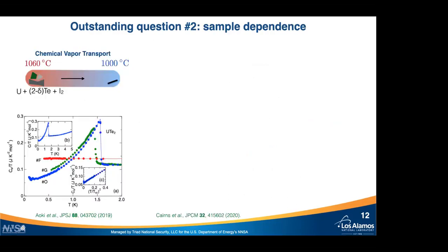The second outstanding question is sample dependence, as I alluded to during the talk a few times. Sample dependence is an issue that is pretty much always present, right, in condensed matter physics. These samples are grown by chemical vapor transport. So on the hot end, we have a mixture of uranium, tellurium, and iodine. And iodine is the chemical vapor transport agent here. But the interesting thing is that we don't start with a stoichiometric amount of tellurium. So it's not uranium-1, tellurium-2. No, it's uranium-1, tellurium-1.5, or something nearby. So why is that?